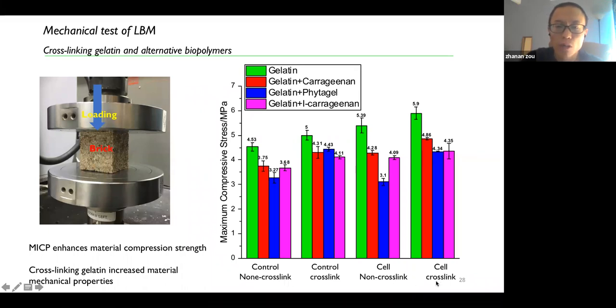So if you compare the columns between different colors, for example the first four columns, you can see that adding a little bit of polysaccharides into the system will slightly reduce the mechanical property. However, it's not a dramatic reduction. If you compare the same color, which is the same category of material, but in different groups, it's very obvious that the cross-linker has a very obvious enhancement of the mechanical property, as well as the cells. The mechanism of the cross-linking is to make the polymer network more dense, thus having stiffer mechanical property.